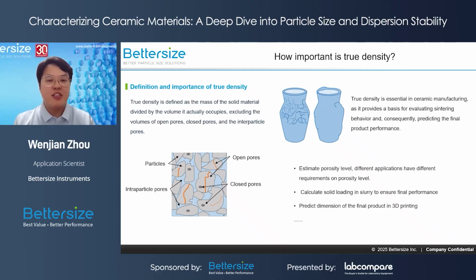True density is essential in ceramic manufacturing, especially in the shaping step, as it provides a basis for evaluating sintering behavior. It can help us understand porosity. By comparing the true density and the bulk density of a sample, we can calculate how porous the product is. This is critical because applications have different requirements on porosity level. For example, structural ceramics are made of dense material for strength, while catalysts need high porosity for specific surface area.